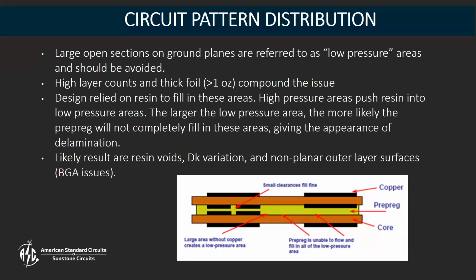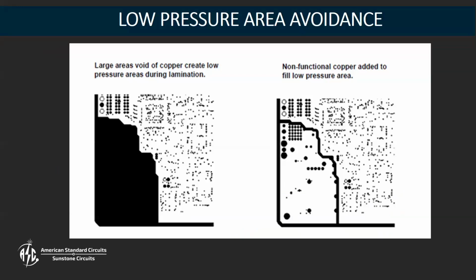And these can tend to create voids of epoxy or resin-rich areas without glass to reinforce it, that can cause issues with delamination or Dk variation, just based on whether it's resin-rich or resin-starved. Sometimes the adhesion, especially if you've got a lot of copper stacked together and you're squeezing a lot of resin out into other areas of the panel, you can actually get areas where the adhesion isn't as good because you're trying to adhere glass to, say, copper, or copper to copper in some areas, and don't really get the good adhesion of the epoxy. So trying to keep, again, balanced and symmetrical.